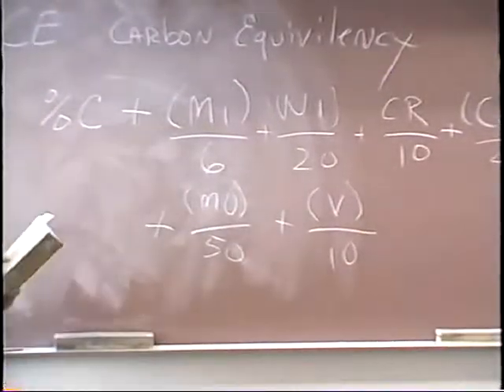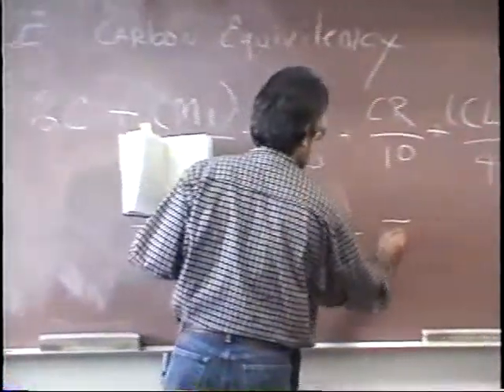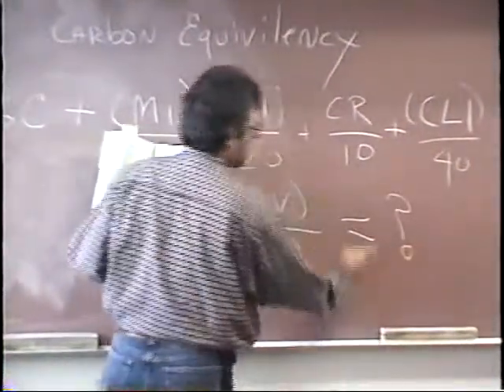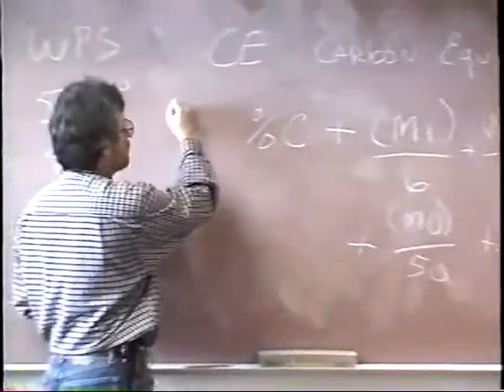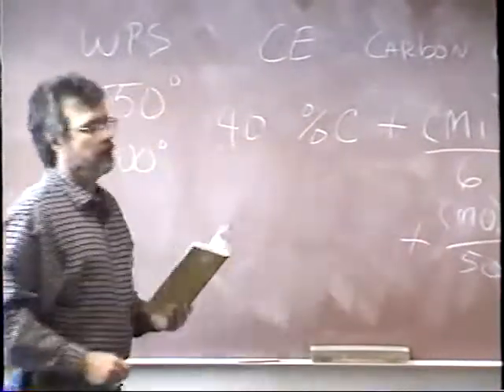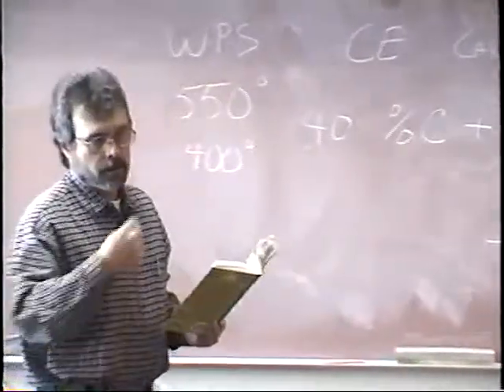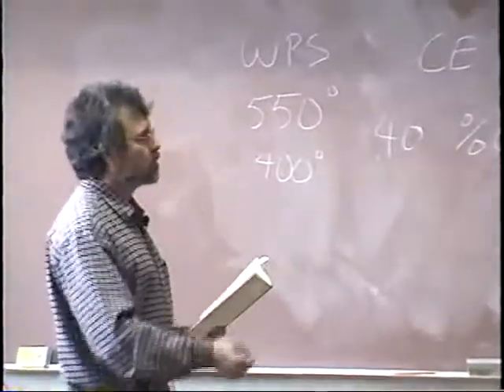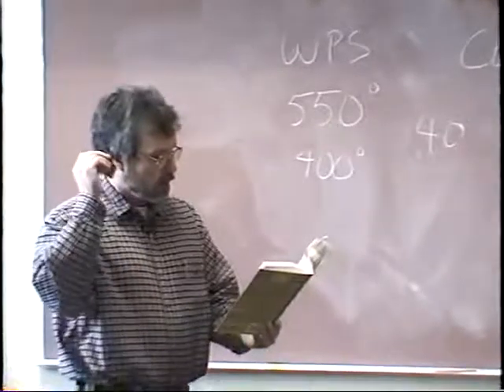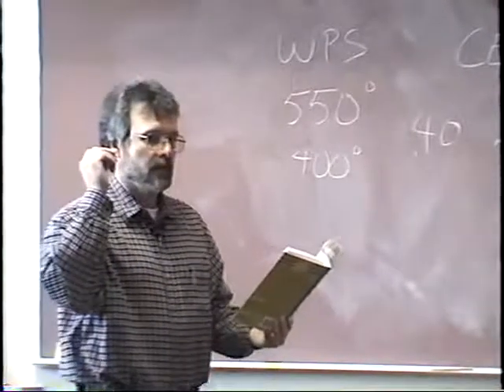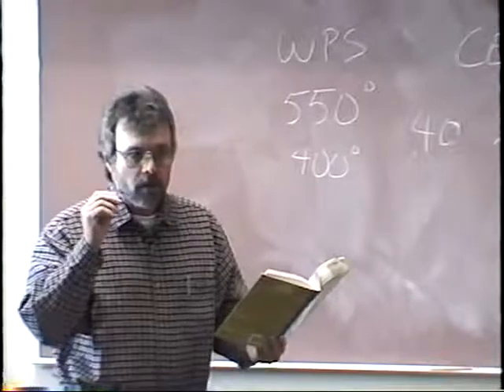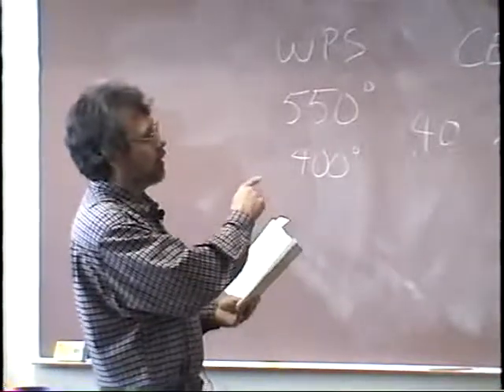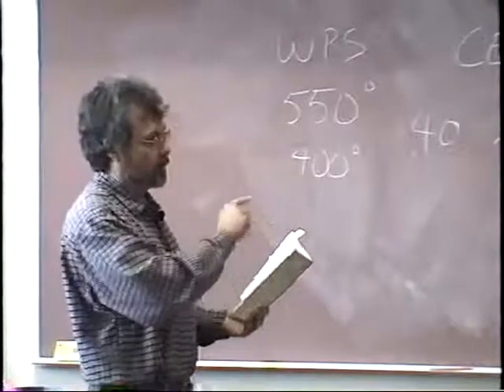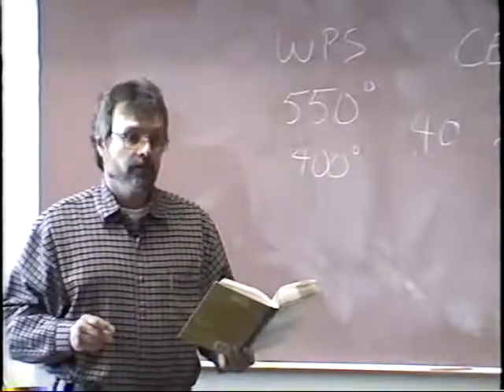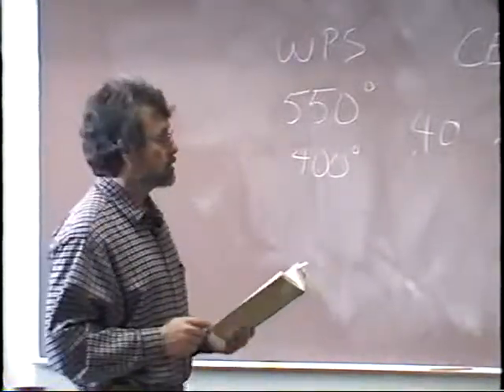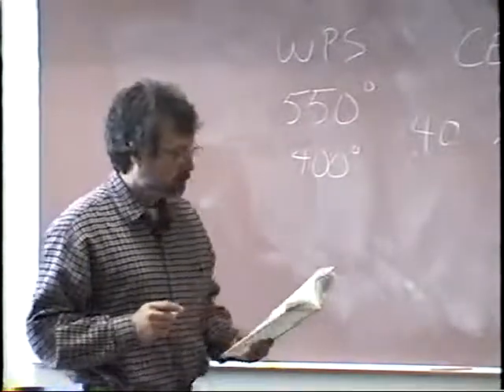If you do these calculations, you'll come up with a carbon equivalency. And if that carbon equivalency is 40 or above, then it's got to be preheated. Interpass temperature's got to be watched. You may have to post-weld heat treat it. And in your text, when you come to take the test off this chapter, there is a question in there that gives these percentages, and you're asked to calculate what that carbon equivalency will be. So when you're ready to take the test, bring a calculator so that you can do that.